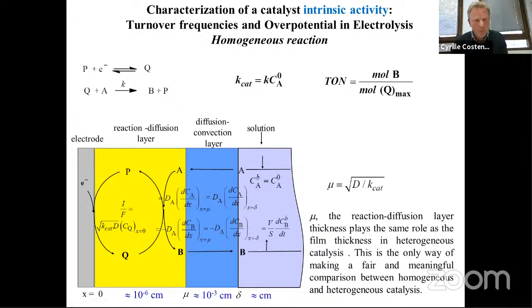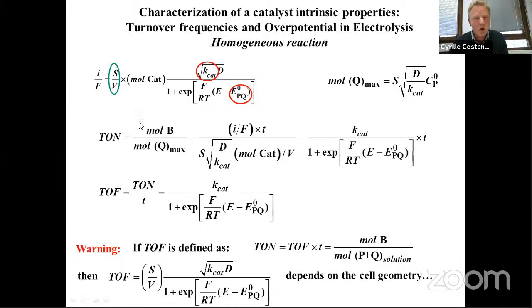So what matters is the number of catalysts that you have in this diffusion reaction layer. So you have to define the turnover frequency as the ratio of the number of molecules that you create per unit of time divided by the number of molecules that you have in the diffusion reaction layer. Okay? And it's not simply the current that gives you this information, because again, as you can see from the expression, the current also depends on the cell geometry.